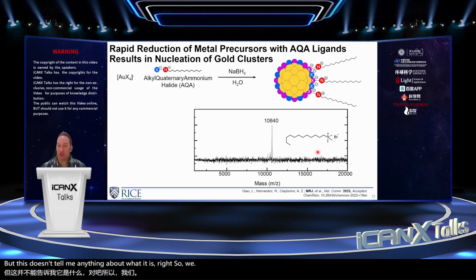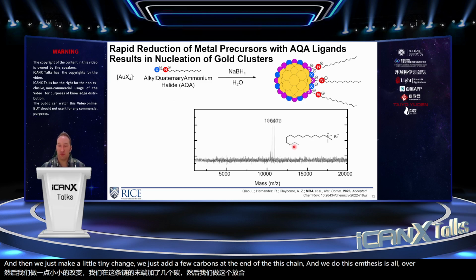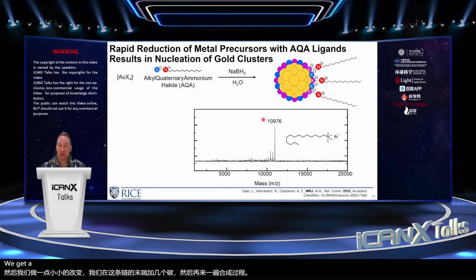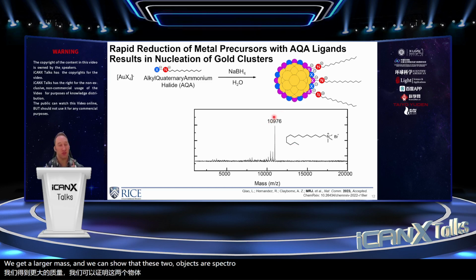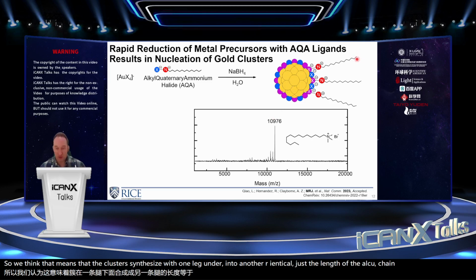So we noticed, however, if we synthesize the cluster with this ligand, and then we just make a little tiny change. We just add a few carbons at the end of this chain, and we do the synthesis all over again. We get a larger mass, and we can show that these two objects are spectroscopically identical. So we think that means that the clusters synthesized with one ligand or another are identical, just the length of the alkyl chain is slightly different.